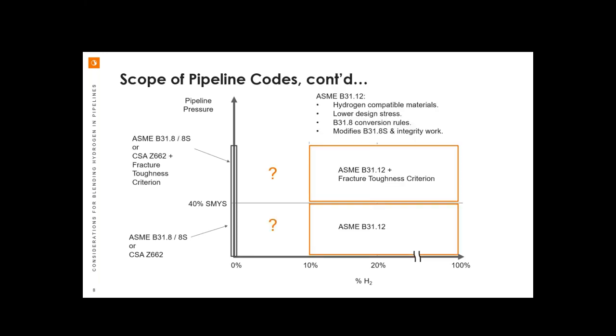Okay, that worked. But when we look at hydrogen, we have ASME B31.12, which could be argued is applicable for both US and Canada for various reasons. And what we see is that there's a similar delineation. And that delineation is at the 40% SMYS value, above which we have a fracture toughness criterion like B31.8. It's just a different criterion, and for the same reasons.